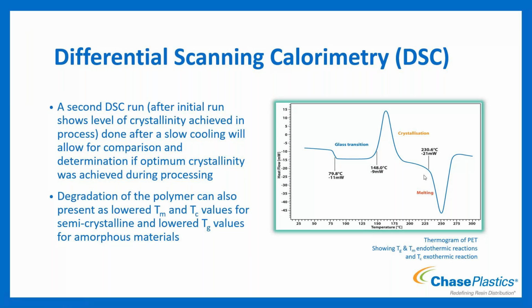You'll have to check. Sometimes they will flip these charts as well. You'll have to pay attention to the flow. So if it's going into the negatives or lower values, it's taking in heat. And so the polymer is taking in heat. It's going through an endothermic reaction. If it's a higher value, it's giving off heat. And so an exothermic reaction. Sometimes they'll flip it, so the melting will be a peak upwards versus down. So just pay attention to the axes to see which one it's showing you. But a great way to determine these different thermal transitions for our materials.